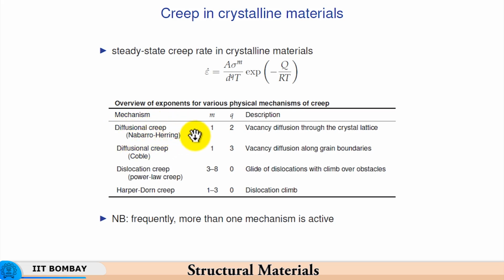in diffusional creep, Nabarro-Herring creep. So, diffusion is a major contributor to the creep process. Vacancy diffusion through the crystal lattice will take place, because vacancies are the ones which diffuse through the crystal lattice. So, vacancy is actually something that is present at the grain boundary. What we mean by vacancy diffusion is that an atom moves to the vacancy at the grain boundary, creating a vacancy in the crystal lattice, which in turn attracts a neighboring atom, which gets into that vacancy, and then the vacancy therefore diffuses through the crystal lattice from where it was generated, where it was born, until it reaches the grain boundary once again.